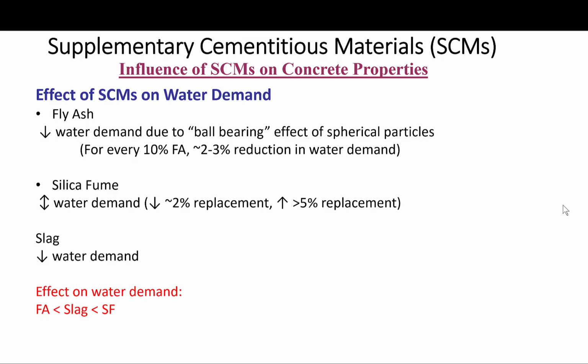Okay, so the effects of SCMs on water demand. How does that happen? Fly ash decreases water demand, basically due to the ball-bearing effect of the spherical particles. So for every 10% replacement of fly ash, there is a 2 to 3% reduction in water demand. Reduction in water means better durability.